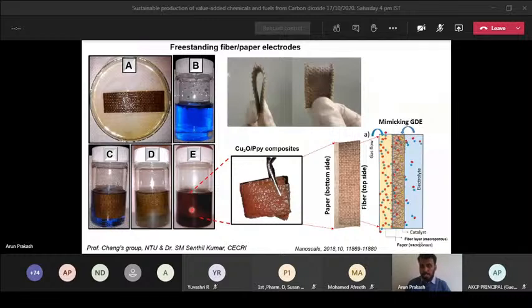The main advantage of this one is that it has fibers and a lot of pores, so this can act as a GDE, not an exact GDE, but it can mimic a gas diffusion electrode. And this is highly flexible, and here you can observe the fiber electrode after coating with copper-based material. Mostly copper-based materials, cuprous oxide or cupric oxide, are brown in color, so you can observe the brown color. So when you have a fiber electrode and you are feeding your carbon dioxide to the fiber surface directly, we can get the CO2 reduction efficiency in a much more efficient way.